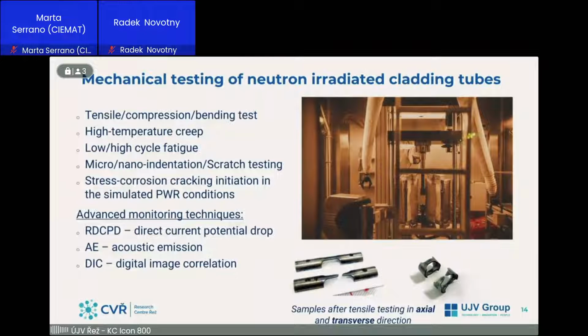Going to our second group in our department, which is mechanical testing group of neutron irradiated cladding tubes in hot cells. So we do the standard mechanical testing as well. We develop the new methodologies mainly for evaluation of ATF claddings. So we do tensile, compression, bending testing, high temperature creep, low or high cycle fatigue. As well we do micro and nano indentation and scratch testing of claddings and ATFs. And we have in hot cells the autoclave for stress corrosion cracking initiation in the PWR conditions simulated.